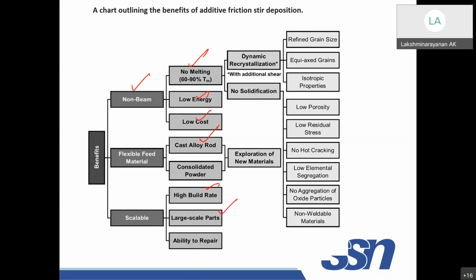advantages over other processes. If you consider the properties, as I told, the material will undergo dynamic recrystallization, which will cause refined grains, and also equiaxed grains. If you see grain morphology, if you have columnar grains, the properties will be entirely different. If you have equiaxed and fine grains, equiaxed in the sense that from the center of the grain to the boundary, the distance is almost equal, right? That's why equiaxed grains always have very good properties, and the property will be isotropic because it is not localized deformation, it is a bulk deformation. So the property will be isotropic.